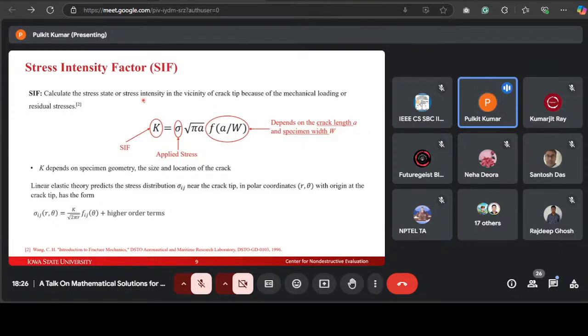Basically, residual stress refers to the internal stress that remains in a material after the external forces are removed, often due to manufacturing processes like welding, casting, and then cooling. These stresses can influence the behavior of cracks or any kind of notches in the material. The stress intensity factor depends on the applied stress, crack length, and the specimen width. Specimen means suppose we have any kind of sample. So this stress intensity factor depends on the sample geometry, the size, and the location of the crack.